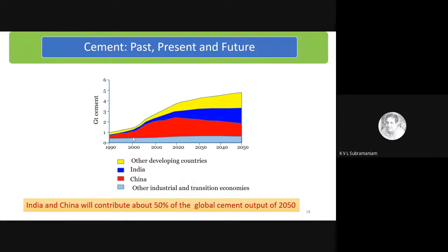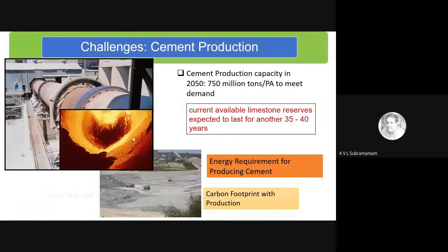Now, what are the challenges with cement production? The challenges with cement production and the anticipated requirement of 750 million tons per annum in 2050, that is the projected requirement of cement. If one is to look at that, our current available reserves of limestone are expected to last only about 35 to 40 years. And this is the grade A limestone. This is the best quality limestone that is currently used in making cement. That's only going to last us 35, 40 years, which means we have to look for alternatives.